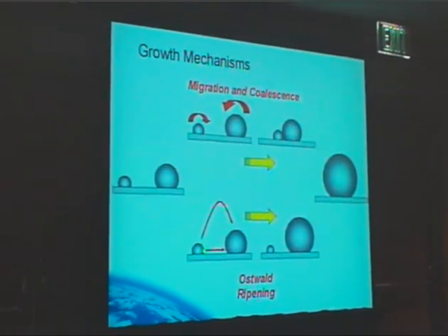Stu pointed out the two predominant mechanisms that are described. There's coalescence, which he very nicely showed can lead to larger particles. And then there's Ostwald ripening, whereby small fragments find their way off of the small particles and migrate to the larger particles, or they can go through the vapor phase and ultimately give you growth of the larger particles. So this is a nice match of what Stu showed. Everything else I'm going to show perhaps is going to be a different perspective.